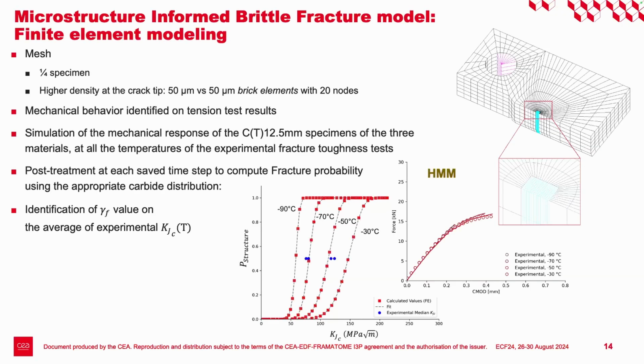So this model is used as a post-treatment of finite element elastoplastic simulations of CT tests. We use this type of meshing, and the mechanical behavior that we use for this simulation is identified on the tension test of each material, the MM, HMM, and IM, at each temperature of the fracture toughness test. And once we have done this, for each time step of the simulation, we can extract the plastic strain fields and the stress fields, and we can compute the fracture probability for a given value of KJ. And we can observe this type of curve for different temperatures for one material.